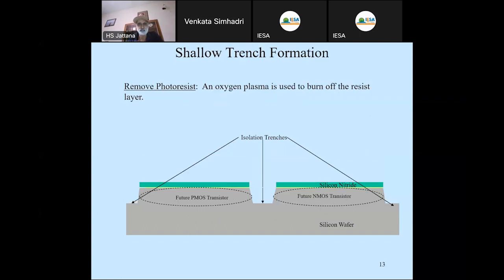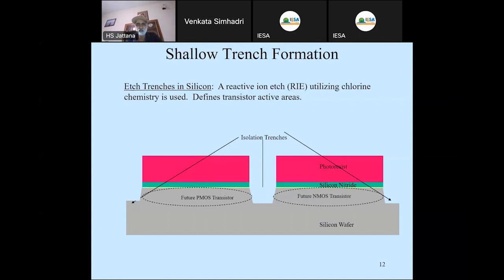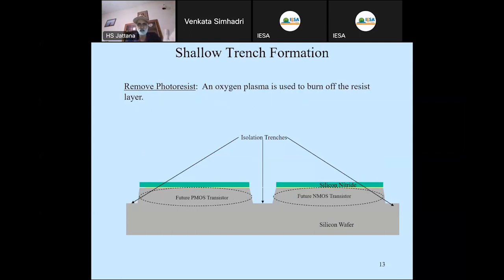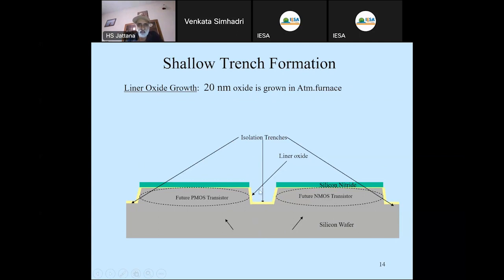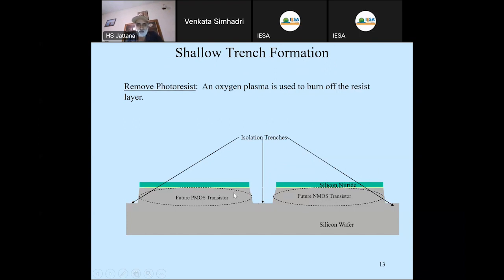So now the next step will be to remove the red, which is a photoresist, whose function is over. We can remove it by oxygen plasma, that has gone. And now this is the trench in the silicon wafer which we are observing, and then we have to fill it. We cannot fill it directly with a high dense oxide. We will first grow by dry oxidation. And this yellow thing you are seeing here, we are growing a liner oxide, 20 nanometer, 200 angstrom. You can see we are growing here. It will not grow on top of the green, because it's silicon nitride. Oxidation cannot take place there. Oxidation will take place only where the silicon surface is visible. So here the silicon surface is visible.